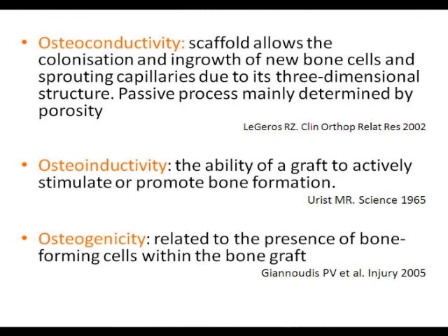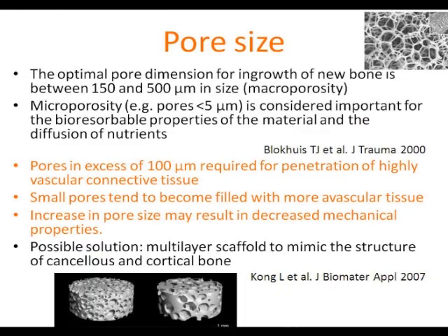The pore size is important because if we have such a synthetic material, it makes a huge difference if I use this one instead of that one, because small pores tend to become filled with more avascular tissue. So they call for fibrotic tissues.